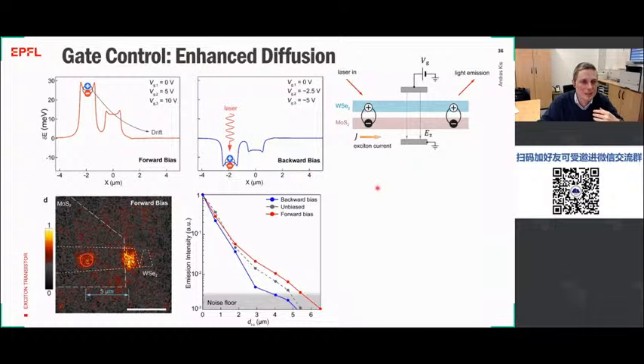And then this worked in a similar way as a diffusion, as a drift force for charge carriers in semiconductors. So it sort of mimicked the idea of having a potential and of modulating the current by introducing some kind of an effective potential. And with these steps, we could then enhance the current of excitons. They could diffuse further, or they could diffuse shorter distances, and this kind of mimics the action of forward or backward bias in a standard semiconductor device.